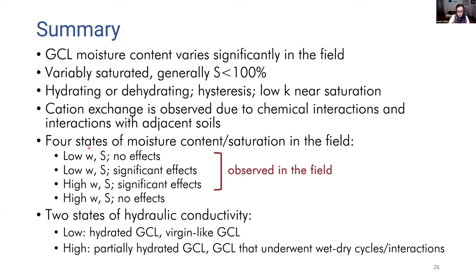And in general, corresponding to these conditions, there are two states of hydraulic conductivity. Hydraulic conductivity may be low in the field over time, for a hydrated GCL or a virgin-like GCL material, or the hydraulic conductivity may be high for a partially hydrated GCL or GCL that underwent wet cycles or interactions with the contained liquids. So it's very important to understand potential exposure conditions in the field. These materials arrive at, again, very low hydraulic conductivities, but that low level of hydraulic conductivity, the containment function, the barrier function may not stay in the field for extended periods of time.